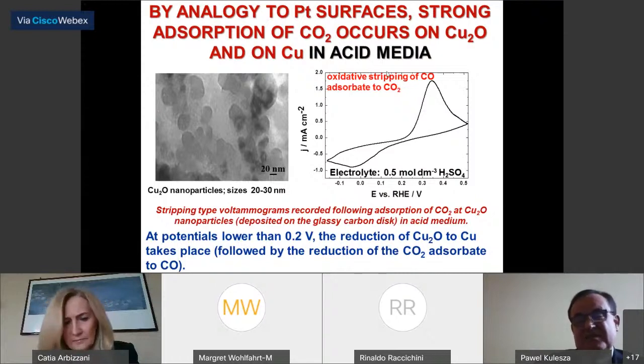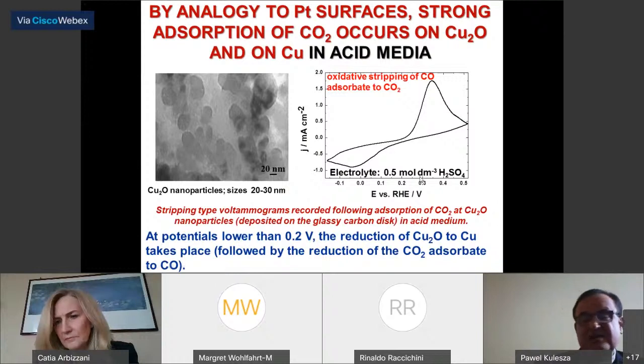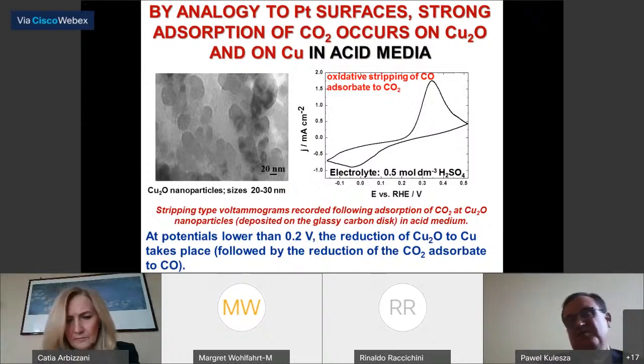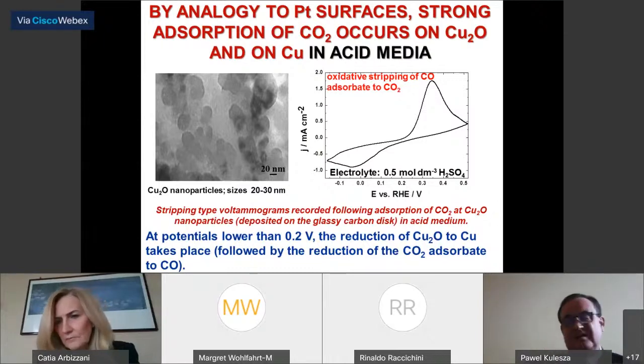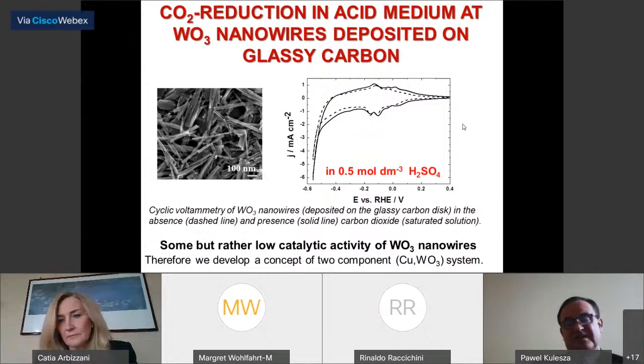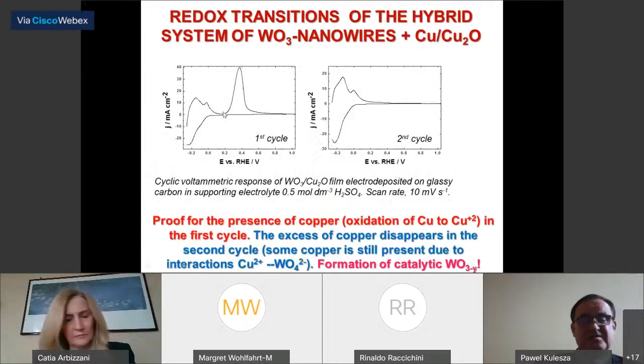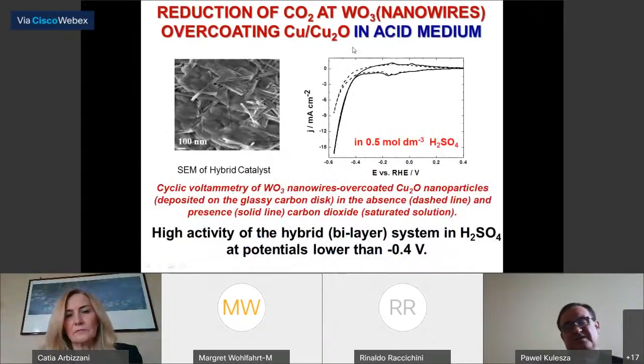And carbon dioxide can be adsorbed on the surface and reoxidized, but only as an interfacial phenomenon. Bulk carbon dioxide will not be reduced, even on copper electrodes, because on copper we generate copper(I) oxide, to make it clear. Using tungsten oxide, briefly speaking, which has some activity because tungsten oxide forms hydrogen-rich bronzes. And these are active, but together with copper, which was electrodeposited, excess was removed, we could observe a very nice situation. So we produce more or less 50-50 hydrogen and reduced carbon dioxide.